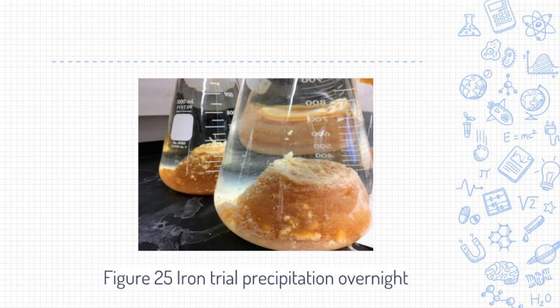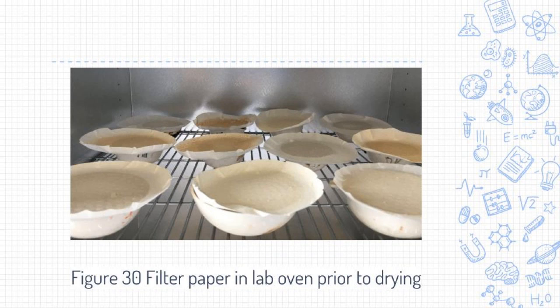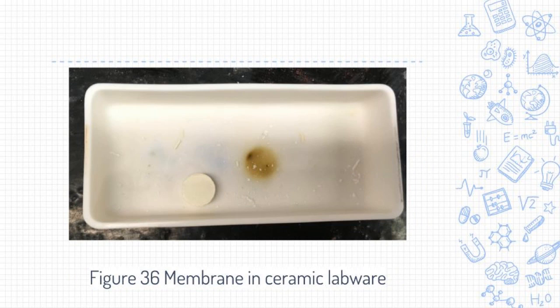We finished heating for an hour, cooled overnight, filtered with Buchner funnels, safely cleaned by evaporating the remaining aqueous solution and deposited the semi-solid remaining to a hazardous waste company. Dried the material caught by the filter paper, calcined to 700 degrees for 6 hours and synthesized into green pellets, which are unsintered membranes. Now, the membranes were ready for testing, and we used this apparatus.